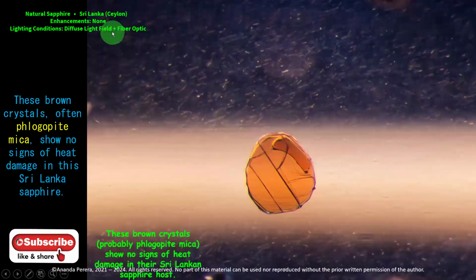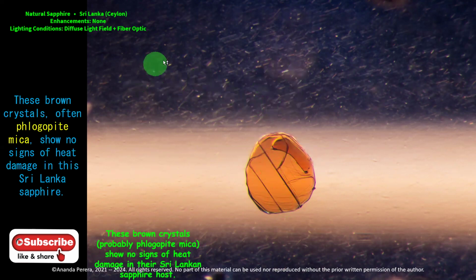What is this? It is a natural Sri Lanka sapphire. Lighting conditions. There are two lighting conditions together, diffuse light field with fiber optic light. So these two lighting conditions give a bright picture here. Look at the inclusions here and the brown crystal here. This brown crystal is Phlogopite. It is a mica, Phlogopite mica. Show no signs of heat damage. No signs of heat damage in this microscopic one and this crystal. So it proves it is untreated stone.